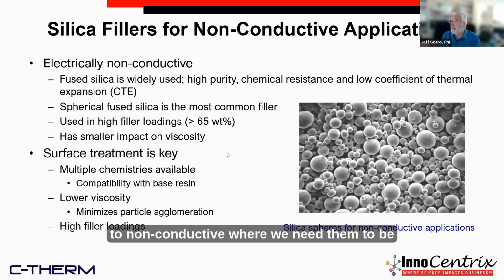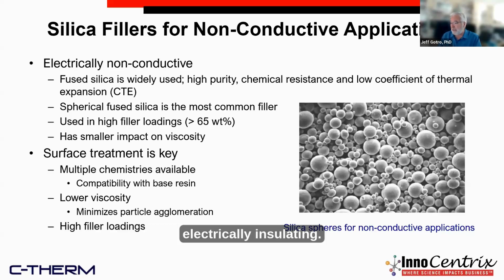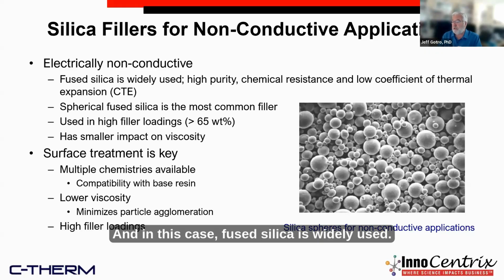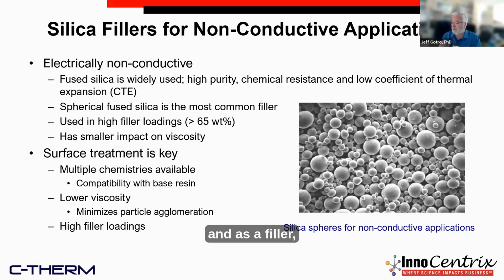Now, let's switch to non-conductive, where we need them to be electrically insulating. And in this case, fused silica is widely used. It's available in high purity, has good chemical resistance, and a lot of times it's used because it has low coefficient of thermal expansion. And as a filler, you can use this to do two things. You can provide modulus, and you can provide some of the coefficient of thermal expansion control.